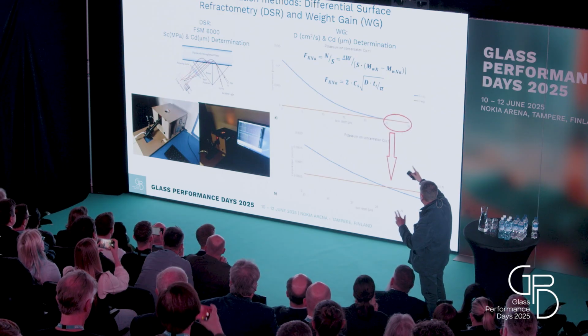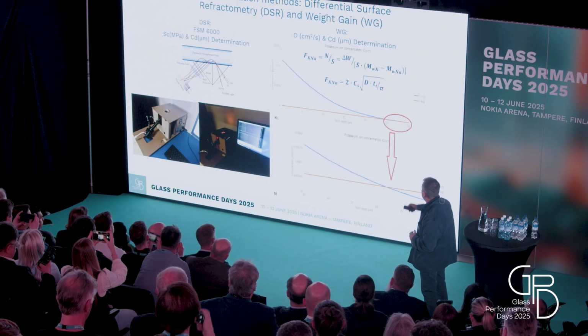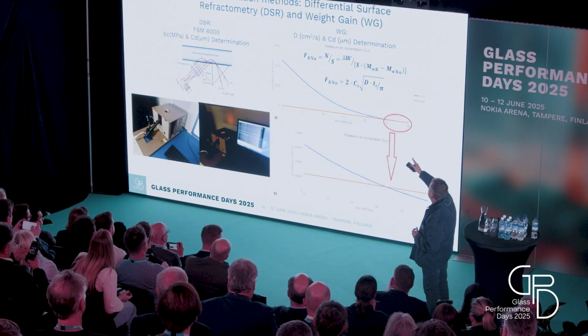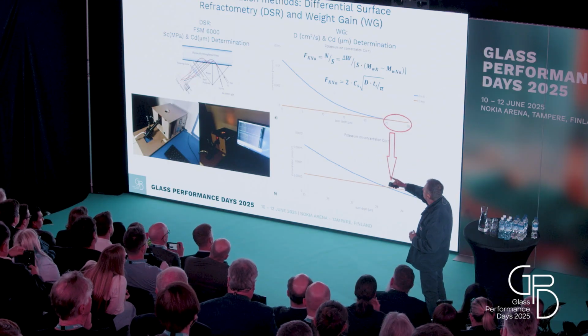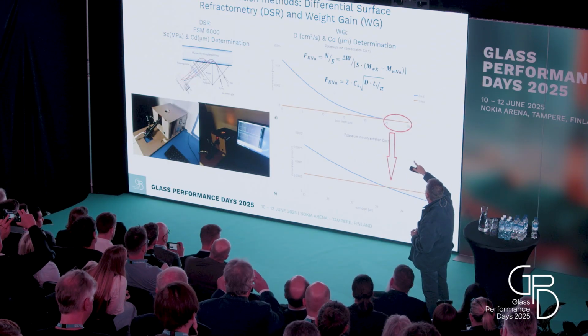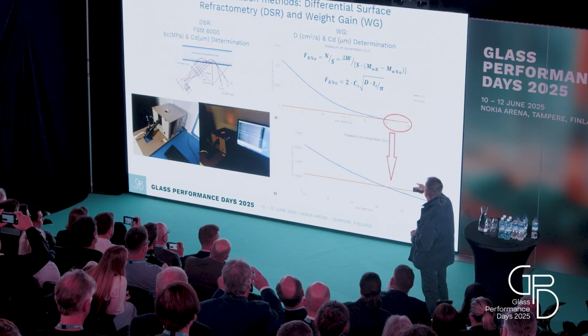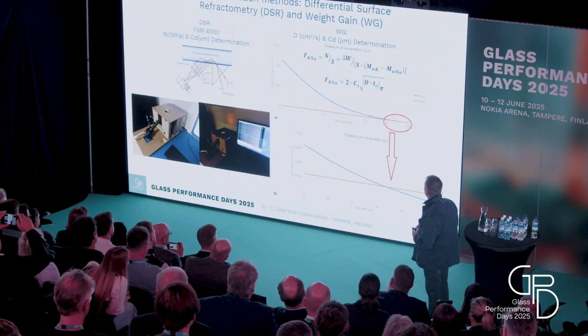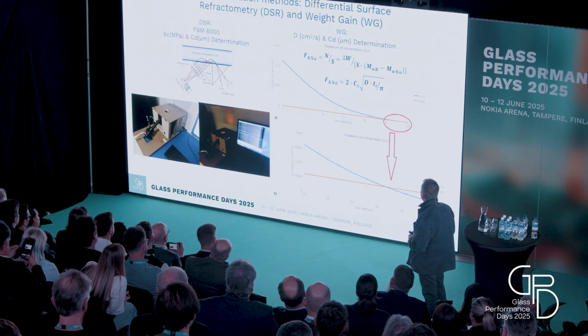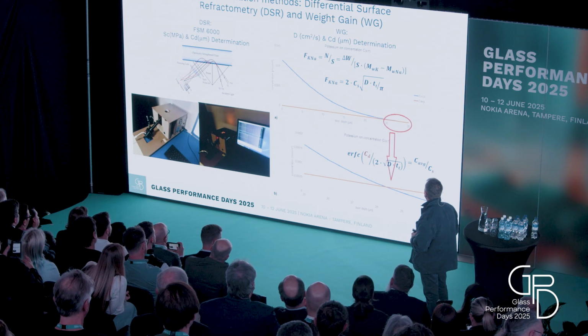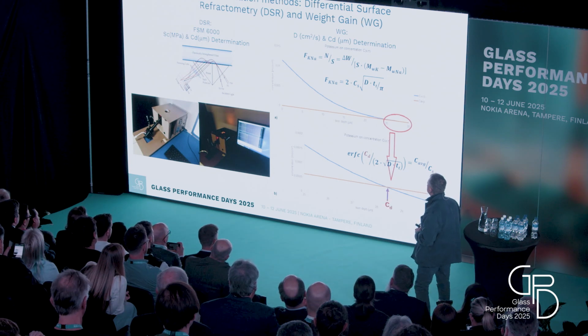And this is a little bit of a workout of the equation, how to get it. So you come with a weight increase, as you have seen before, and then after a few calculations, you come out with a determination of both the interdiffusion coefficient and the case depth. Okay, let's go ahead.